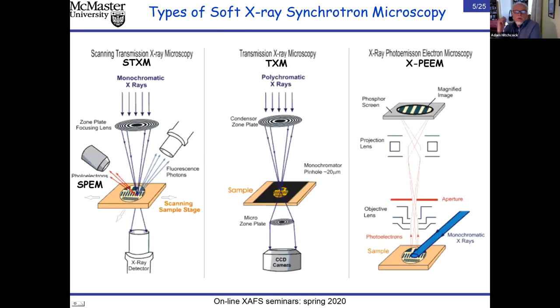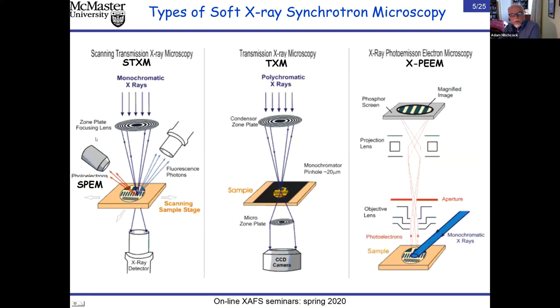How do we make these measurements? In the soft X-ray there are four main classes of microscopy. I'm focusing on STXM—Scanning Transmission X-ray Microscopy—where we use a zone plate to focus monochromatic X-rays down to a small spot in space, then raster scan the sample through this focus while detecting transmitted light to make images. By taking image sequences at multiple energies we obtain spectroscopy at each pixel.